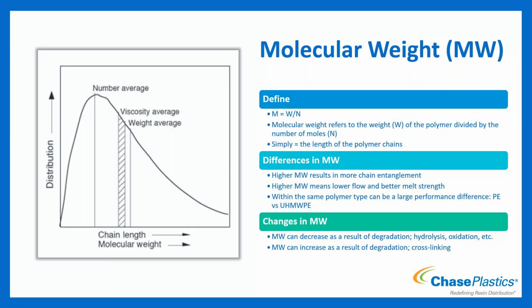The other thing to be noted here would be same polymer type can have vastly different performances or very large performance differences depending on its molecular weight. So an example of that would be your polyethylene. So you think of your high density, your low density, just very commodity based, great for a lot of different things, but we wouldn't consider it an engineering polymer by any means. Versus your ultra high molecular weight polyethylene used for very high abrasive wear type applications. For a while, they're used for the non-ice skating stuff. So quite a difference from the polyethylene that you would see used as more of like a tote or something like that. Vastly different, all because of our differences in molecular weight.